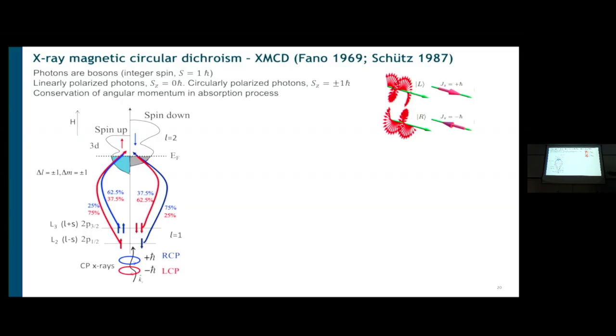And you also see something interesting. If you go from L2, which is L minus S, to P1/2, to the other pair in the spin-orbit split P states, which is L plus S, which is 3/2, you see that RCP, blue, excites mostly 75% spin up here. The other edge is spin up instead of spin down, because the spin-orbit coupling in these core levels has a different, opposite sign. So you produce opposite signs of polarization. This will become important when I show you some rules that you can use on X-ray absorption across these two core levels to actually get information on orbital magnetization.